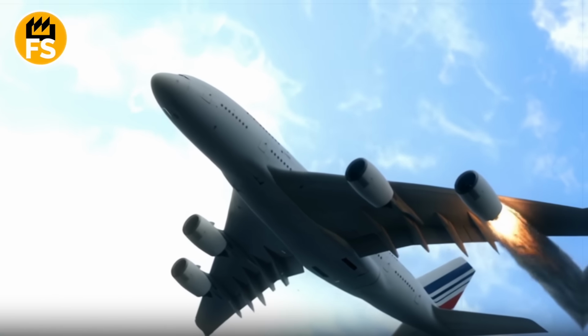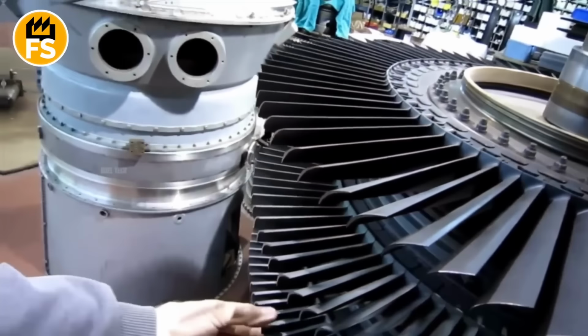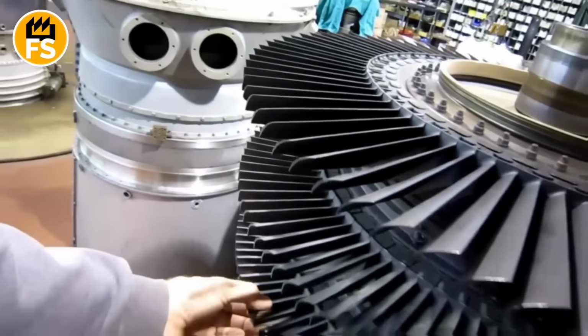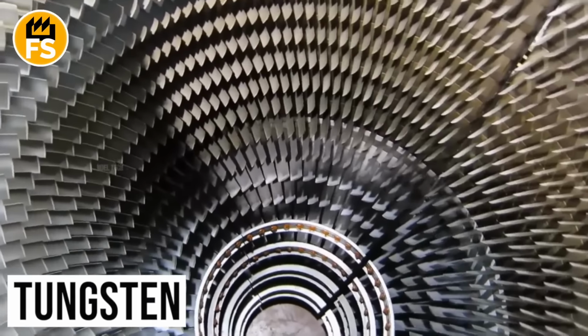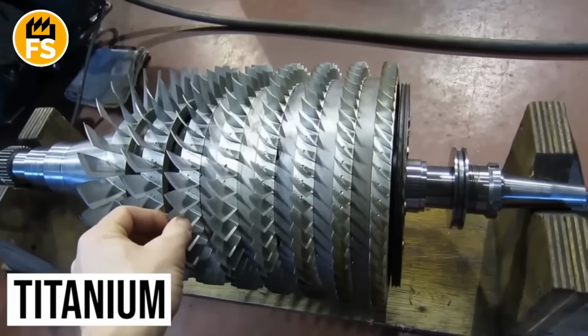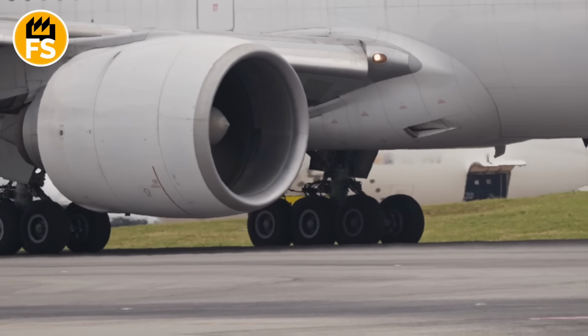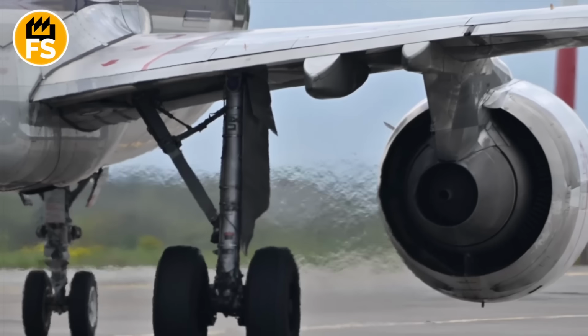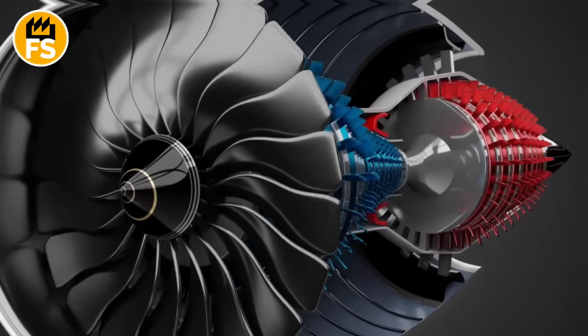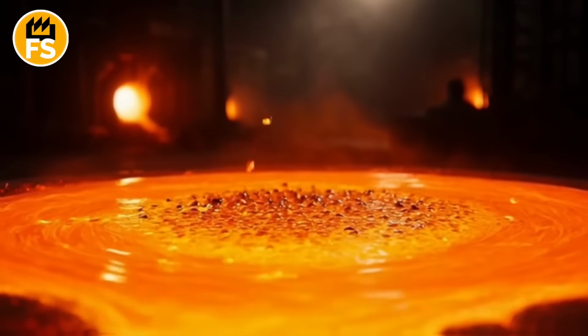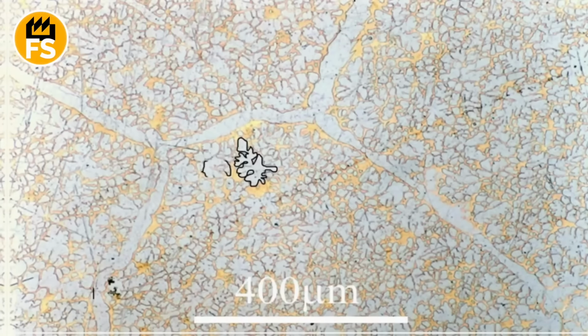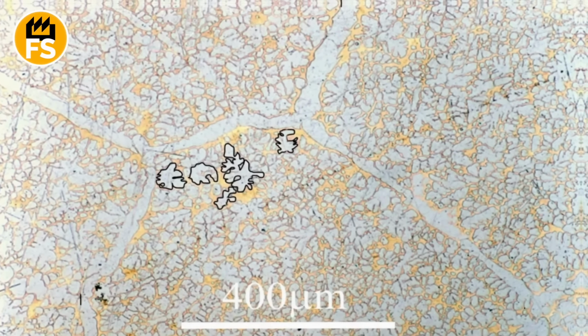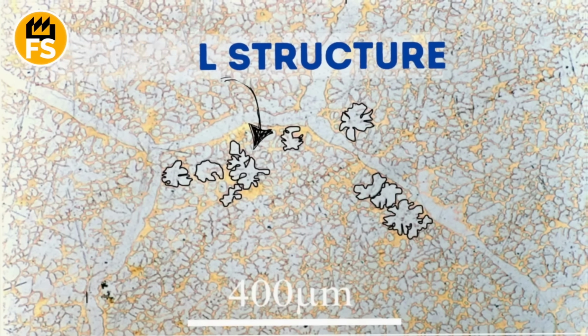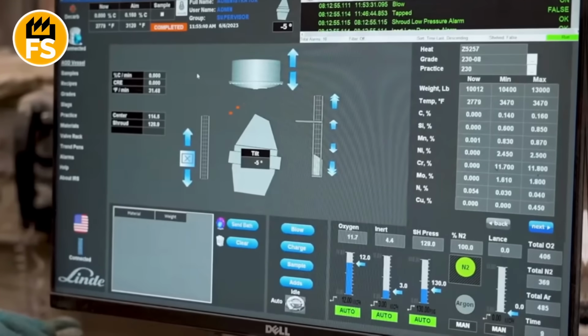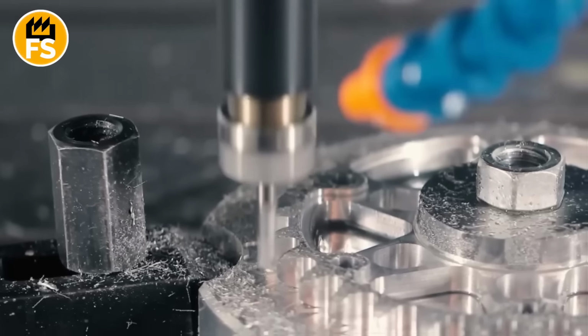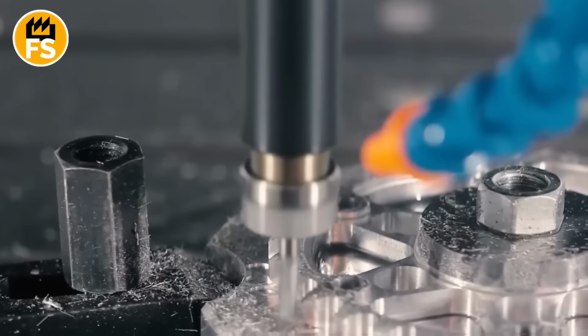Nickel superalloys, the primary material for turbine blades, contain nickel, chromium, cobalt, tungsten, molybdenum, aluminum, and titanium. But even these complex alloys couldn't withstand temperatures over several thousand degrees for extended periods, until they added rhenium. Rhenium does something remarkable. It dissolves into the nickel matrix of the superalloy and prevents defects from moving through the crystal structure at high temperatures. This is called creep, the gradual deformation of metal under load at temperature. All metals creep, but rhenium slows this process down by several times.